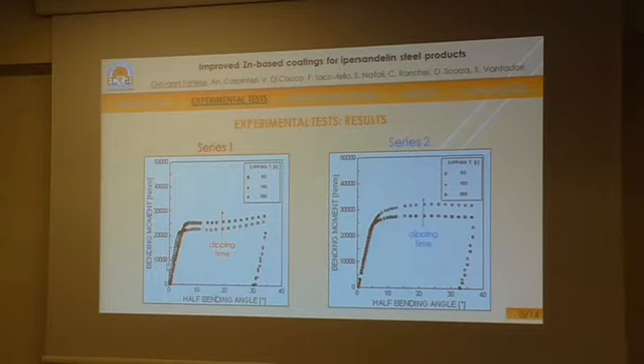Experimental results related to the above bending test are here shown in terms of bending moment against half bending angle for each considered dipping time. As can be observed, decreasing dipping time leads to higher bending moment values, and such effect is more pronounced for series 2 specimens due to their higher bath reactivity.